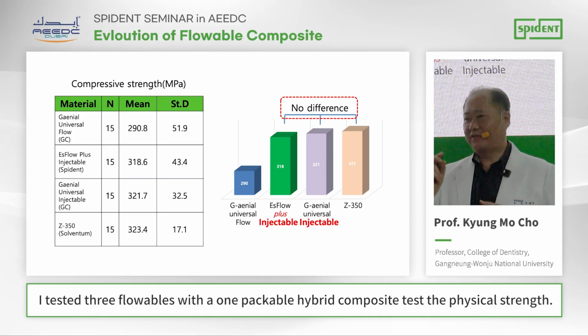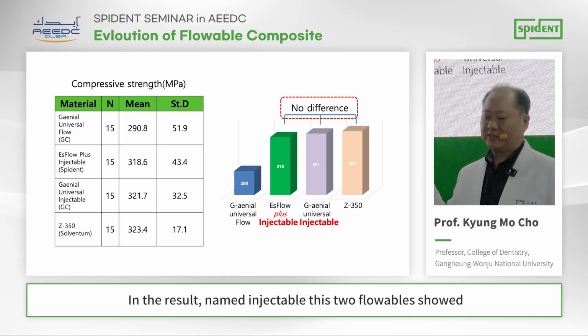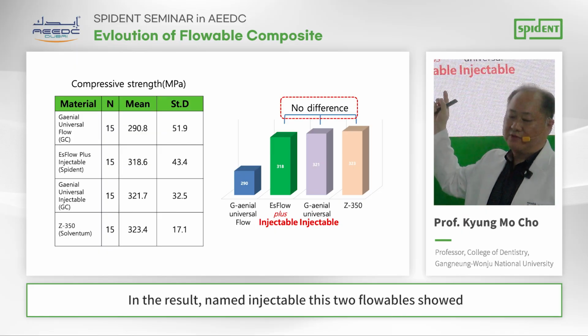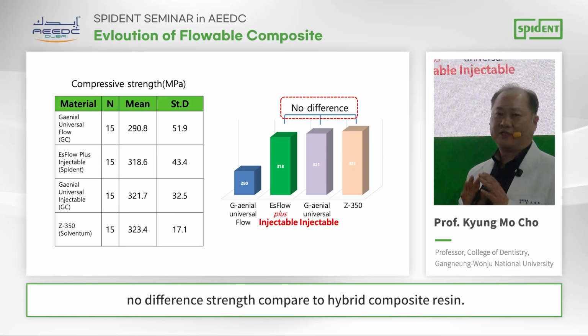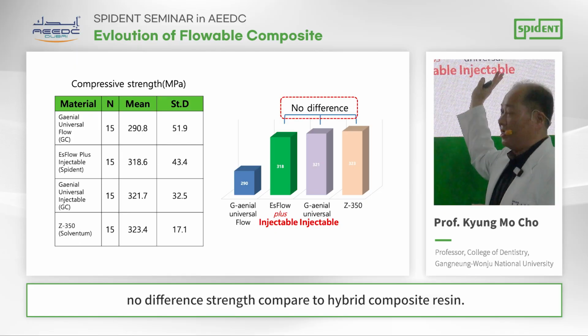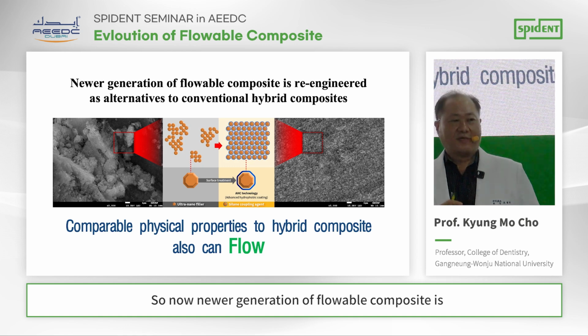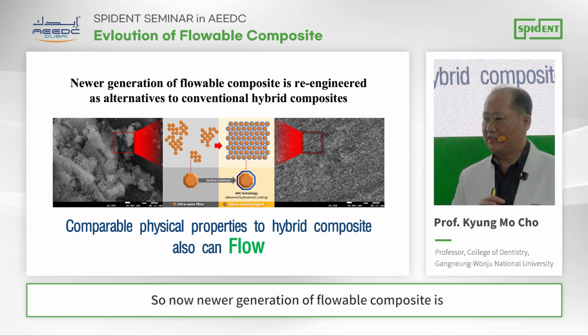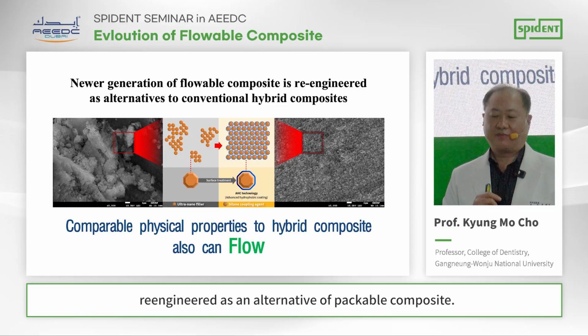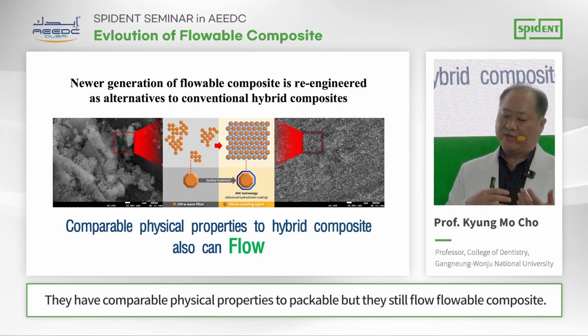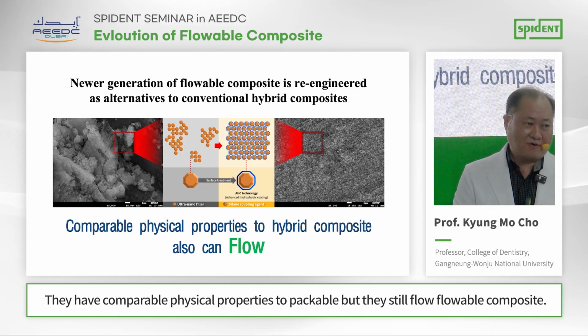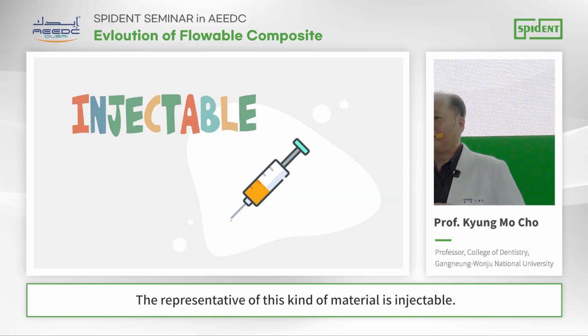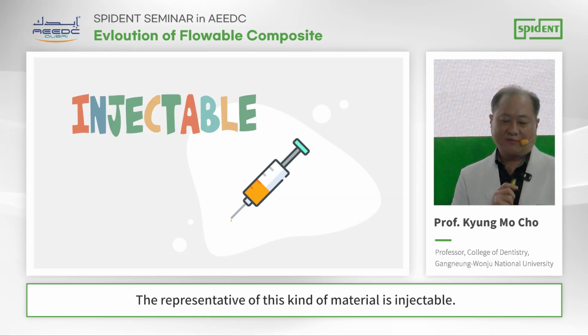Two years ago, I tested three flowables and one packable hybrid composite to test physical strength. In the result, two of these flowables, named Injectable, showed no difference in strength compared to the hybrid composite resin. So now a newer generation of flowable composite is re-engineered as an alternative to conventional hybrid composite. So they are comparable. They have comparable physical properties to hybrid composite, but they still flow as a flowable composite. The representative of this kind of material is Injectable.